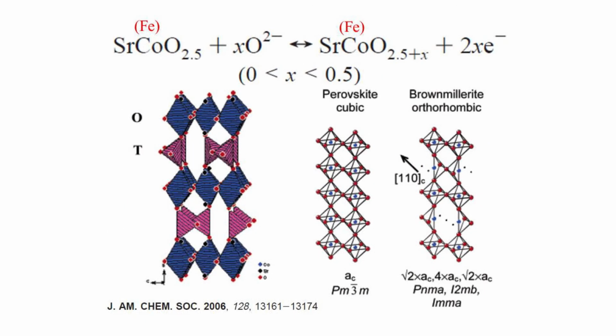So the first one is a mixed oxide, strontium cobalt oxide, and its particularity is that it is able to change the stoichiometry from oxygen 2.5 up to oxygen 3, which is a huge amount of possibility of oxygen intercalation. And even more interesting is the fact that this material, but also the homologue with iron, so if we put iron instead of cobalt, it will work in the same way, and it is able to do this job at room temperature in electrochemical conditions.